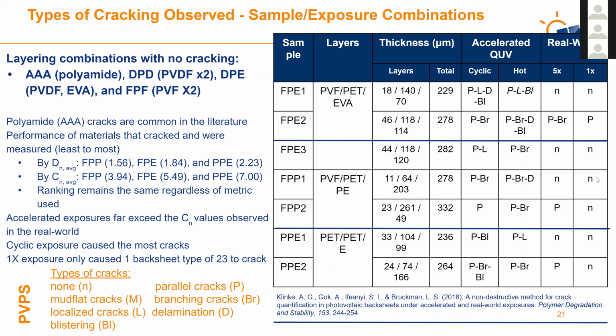And what we found is that there was very little cracking at just our 1x outdoor exposure with one backsheet type crack, but that was only for 12 months. And so it was PVF PET EVA layer, this FPE2.